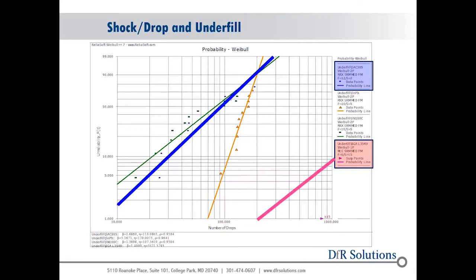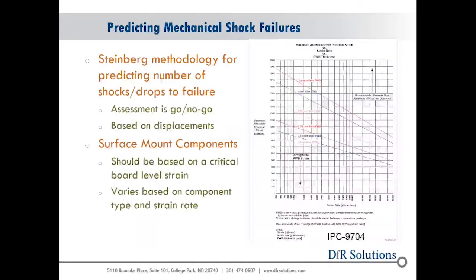But now when we get to underfill, we have 0 failures for the underfill device. So you can see just a huge impact using underfill. Now, underfill is great for vibration and mechanical shock, but you have to make sure when you're selecting an underfill, especially, typically what we're seeing is if I'm putting my product into an environment that has high shock levels and high vibration levels, it probably also has high temperature changes or thermal cycling criteria.